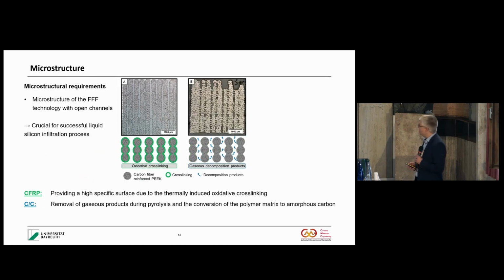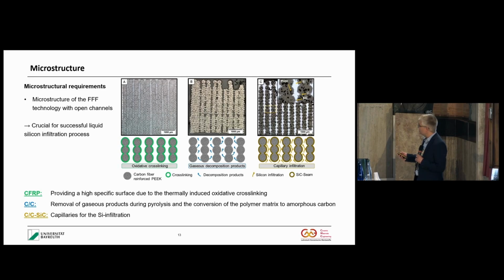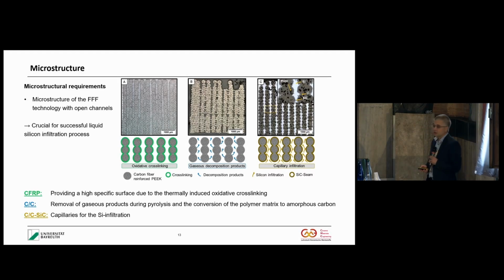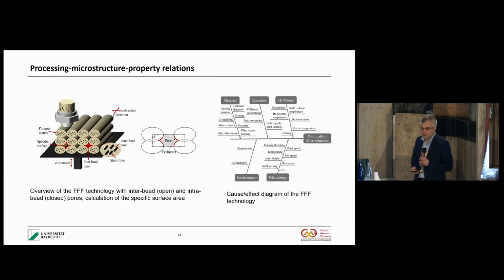The other aspect is that during the pyrolysis, you also induce porosity. This is a study from 2021, some years back. You have to have porosity later on during siliconization, but of course you want to reduce the porosity as much as possible. In this case, you see the porosity was quite large, and the white lines are the residual silicon, but nevertheless, this was the first study in 2021 showing that we can produce carbon fiber reinforced silicon carbide using this process.